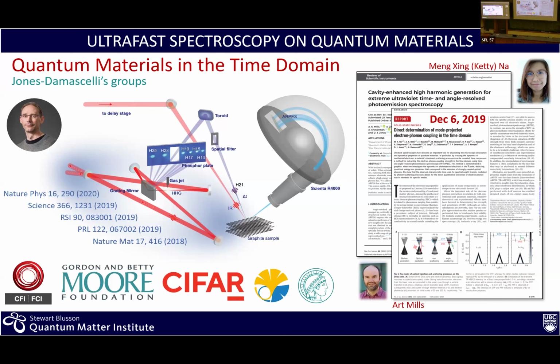And that is a challenging experiment because in order to do photoemission, you need photons with an energy of at least 4 electron volts, but in practice 6 eV and higher, basically well into the UV or even better into the extreme UV, to be able to scan all the momentum space. And so that's where David Jones' group comes in. What you see here is a blue UV photon coming onto a sample, but this UV photon is being generated by high harmonic generation in a gas jet. And the challenge there is to be able to come in with a very short pulse and yet have a decent energy resolution.